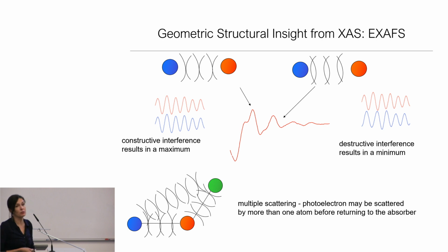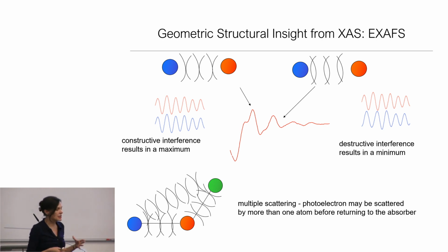But EXAFS itself is a scattering-based approach, right? So when we were talking about the edge, it's a picture that we can largely think about in concepts that we talked about with molecular orbital theory. But now with the EXAFS, our photoelectron wave vector has been ejected to the continuum, and it's now a photoelectron wave that's propagating out, and it's going to get scattered by the electron density of surrounding atoms. And when that happens, the returning wave can be interfering with the outgoing wave either in a constructive or a destructive manner. And that's what gives these sort of wiggles that we know as EXAFS and that we use to report on local metrical structure. And of course, it's not just the photoabsorber and the nearest neighbor, but the scattering can happen off more distant neighbors, and that's what we refer to as multiple scattering.